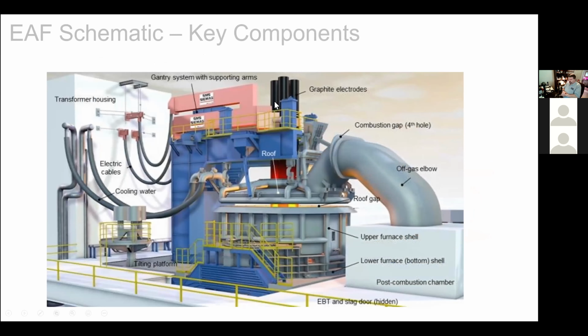So the electric arc furnace is quite interesting. I work a lot with these. This one's an AC furnace. You can see that it has 3 connections, one to each arm from the transformer vault. So this is actually the electrical delta protruding out through the wall of the transformer vault. We use water-cooled flexible cables to connect to the arms. These arms hold electrodes in place, and the electrodes supply power. Because this is 3-phase, we're arcing between one electrode, and the return path for the current is through one of the other 2 electrodes.